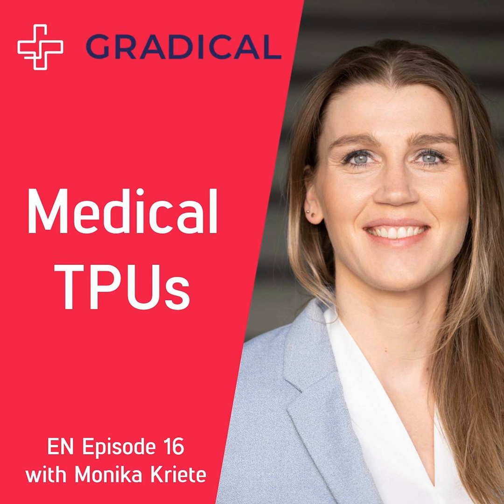Yeah, and just commenting on the stickiness, I would say there are certain trends within a chemistry which goes from very sticky to less sticky, or maybe certain chemistries which are less. But depending on what you're looking for, some of them can be a bit challenging. But I would say the main key requirement, if you look at melt processing TPU, is really to make sure you have the right drying equipment. I still remember when I started my job, I didn't really believe it's mainly this issue which customers face, but it oftentimes really goes down to having the TPU properly dried before melting it up. The reason why that is so important is that if you don't have it dry enough, the moisture present while melting can disrupt the chains of the polymer and lead to reduced physical properties of your final product.